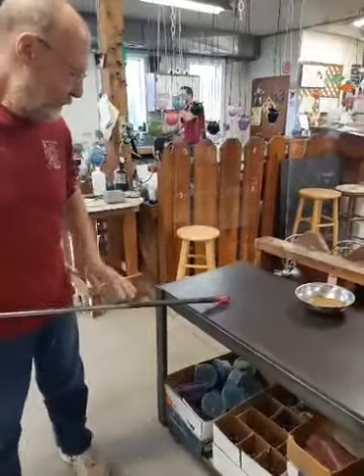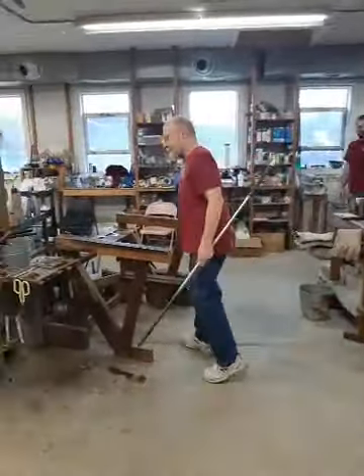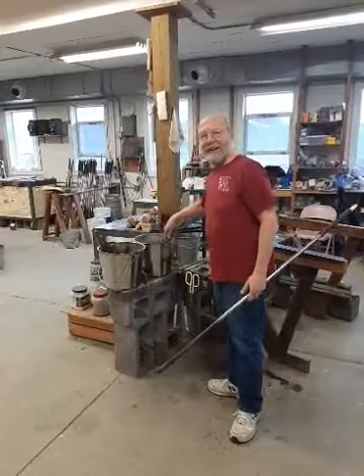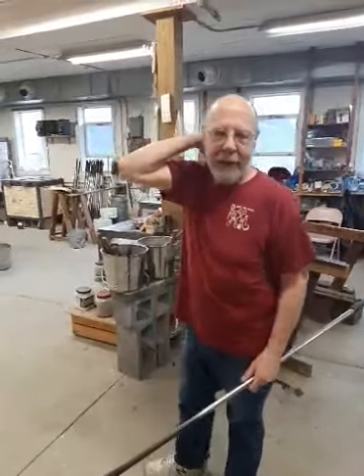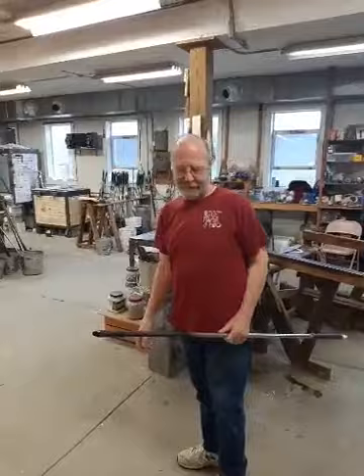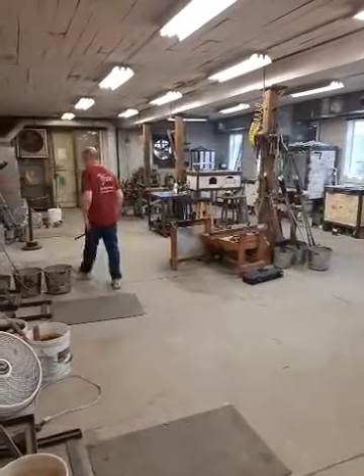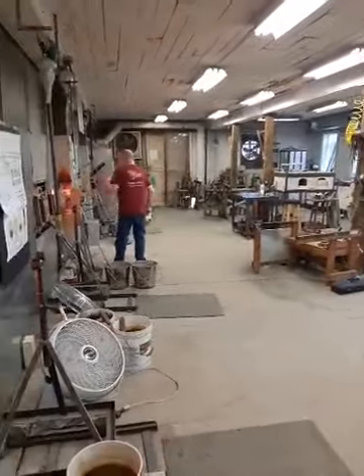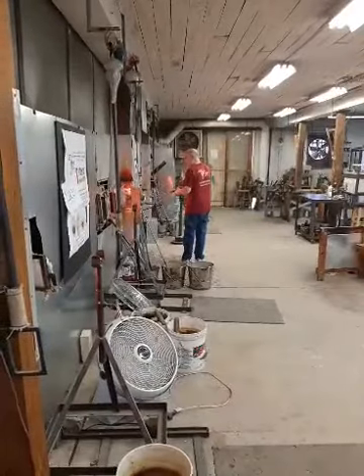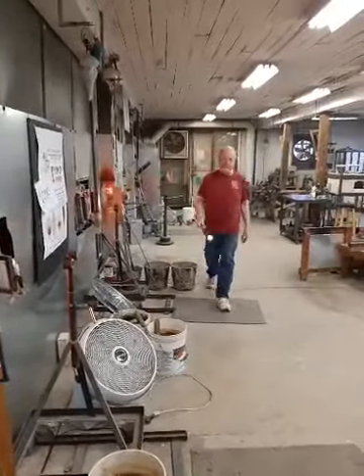Okay, just how many different colors of purple are there? Well, Michelle, I will say that one of the more interesting colors of purple is black, because in the world of glass, I can't say for pure color theory, but in the world of glass, black is actually made from the same thing as purple. It's just so doggone intense with manganese that it looks black. But if we take a black color, something that we've paid good money for black bar stock, and blow it out too thin, it actually looks purple. As far as the rest of your question, in all seriousness, we've got about 3 or 4 varieties of transparent purples, and we've also got a couple of different opaque purples.